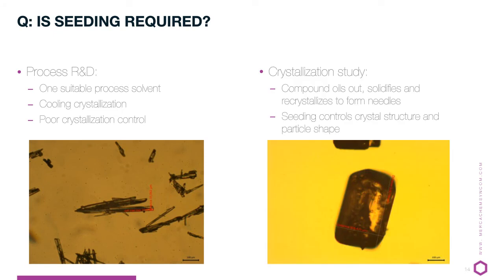From the crystallization study, we got more understanding on how actually the nucleation part of this crystallization worked. It was mainly an oiling out of the compound, and finally it solidifies and recrystallizes in the form of needles. So really control about the nucleation part was not present in this crystallization. In this case, seeding gave more control about the crystal structure as well as about the particle shape. The formed material showed clearly single-sized particles that had a good filtration and drying rate, good bulk properties, good flowability, as well as stability properties. In this case, seeding was required.